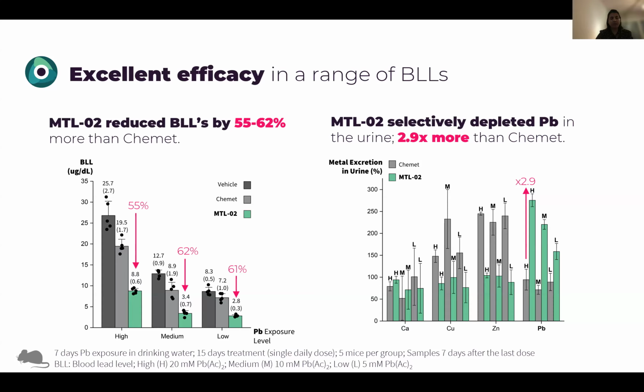And based on this, we have concluded that regardless of the initial level of exposure to lead, in all of the cases, even at low initial blood lead levels, MTL2 manages to reduce blood lead level and, through urinary excretion, significantly more than, of course, untreated mice, as well as the ones that are treated with DMSA or CEMET. So this is clearly an indication that even at low levels of exposure, our MTL2 specifically can be extremely efficacious.